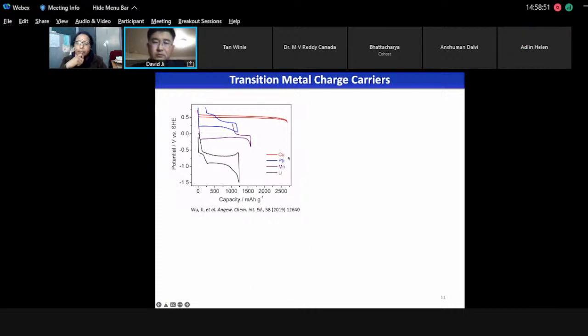So the first example I want to introduce is copper. This is the galvanostatic charge discharge profiles for sulfur electrode. This is probably commonly known. This is for lithium sulfur, right? Lithium sulfur battery has received a lot of attention. I studied that during my PhD time. And then this is manganese, and this is copper.